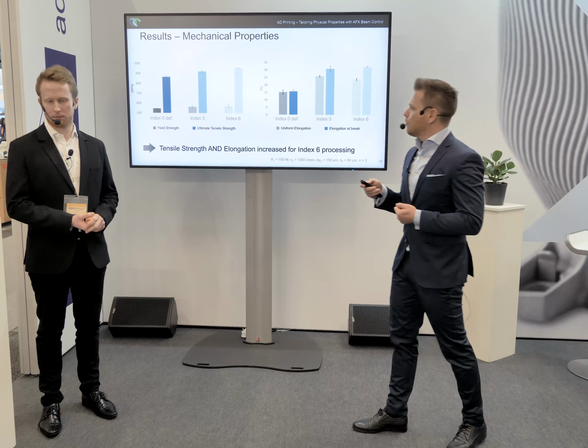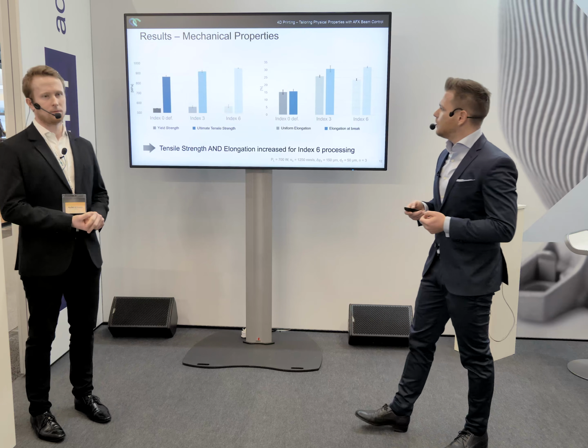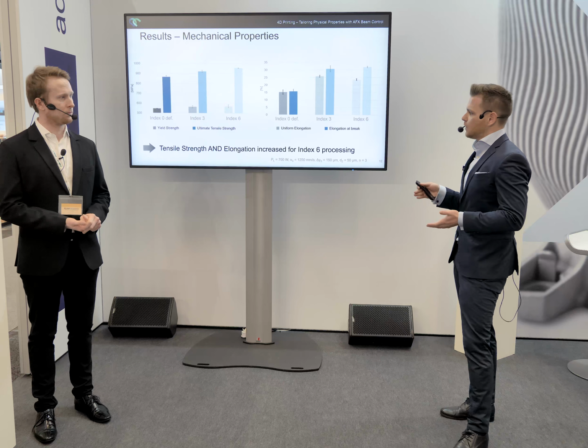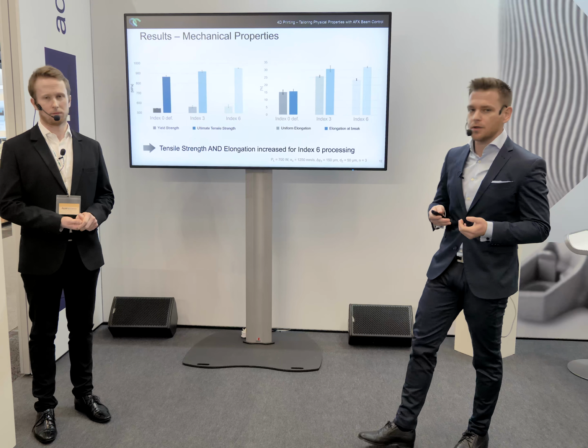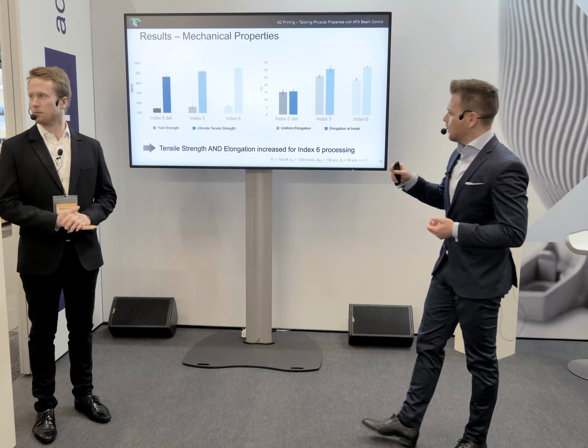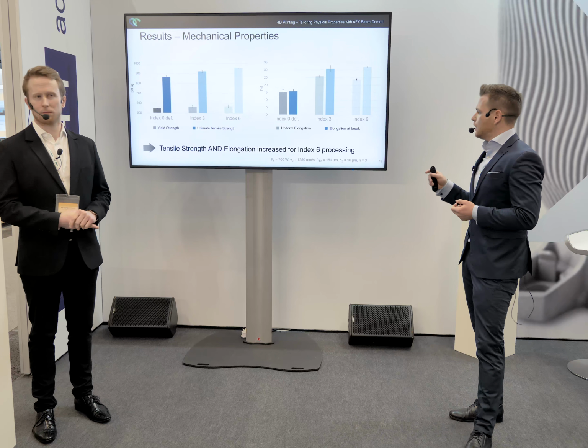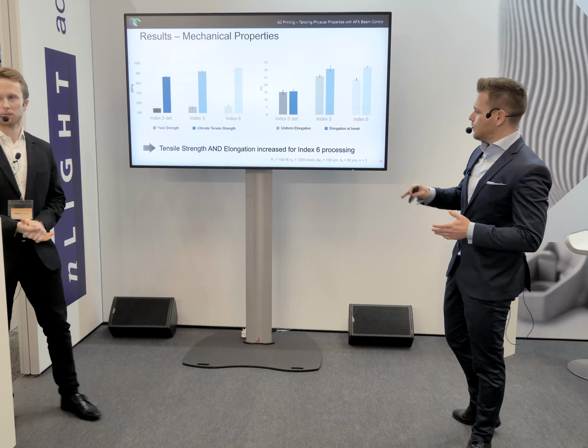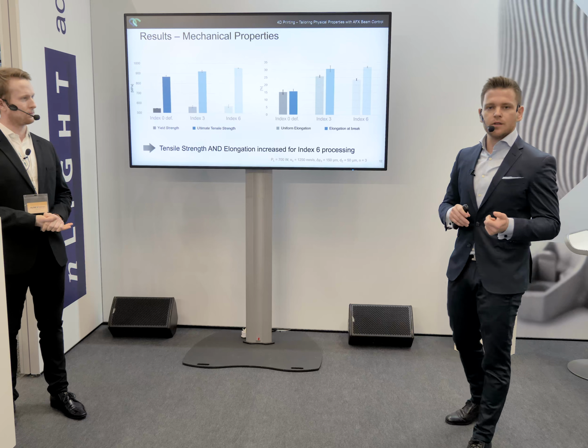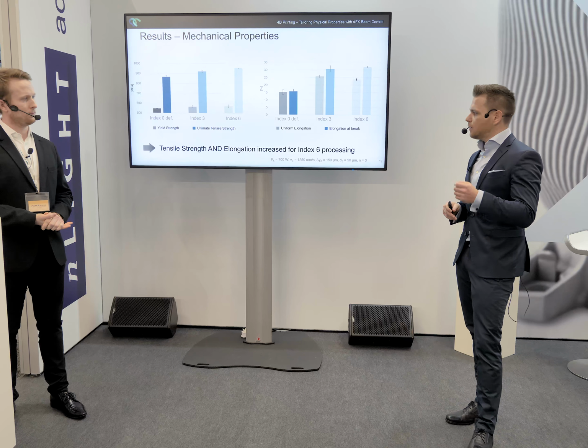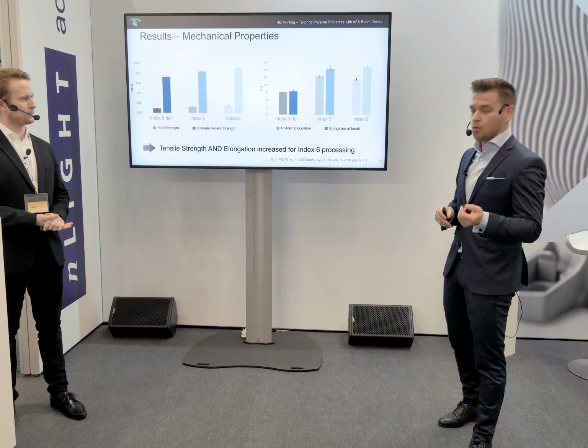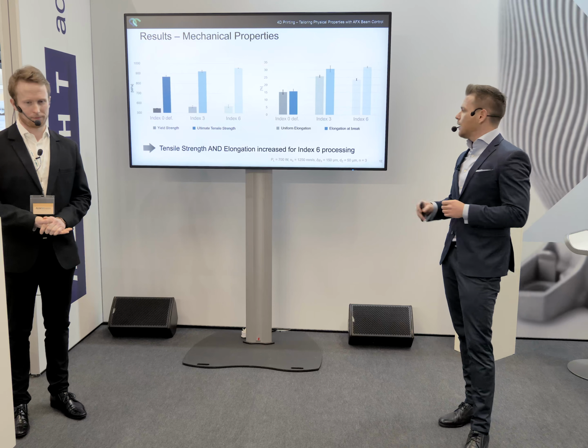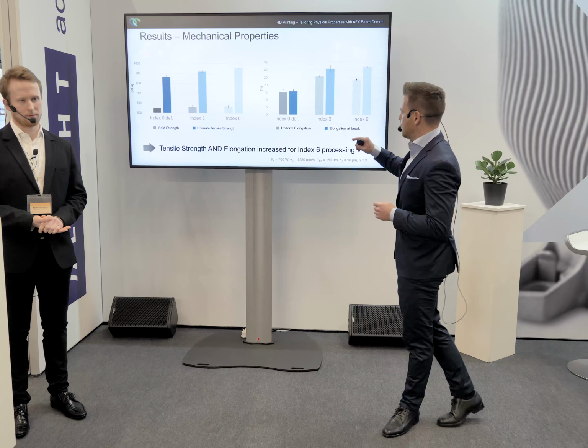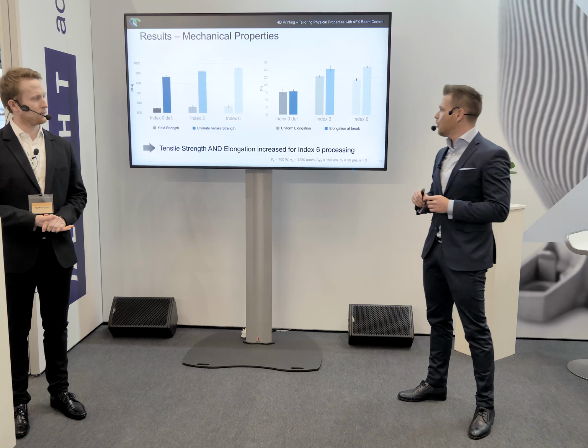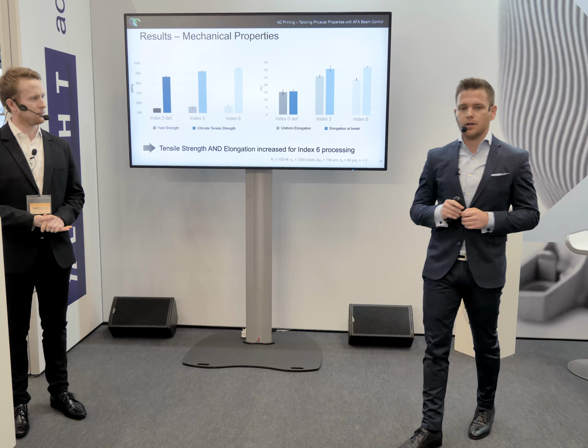The results of the mechanical properties are indeed much greater. So what we can see here is a really interesting thing. On the left side we have the yield strength, on the right side the elongation, and as you may see, by using index 6 we can increase the yield strength and tensile strength as well as the elongation at break. And in comparison to index 0, almost twice as high in the elongation at break.